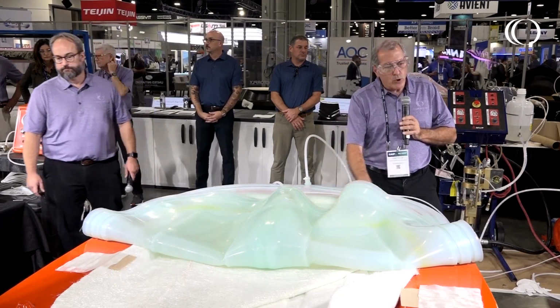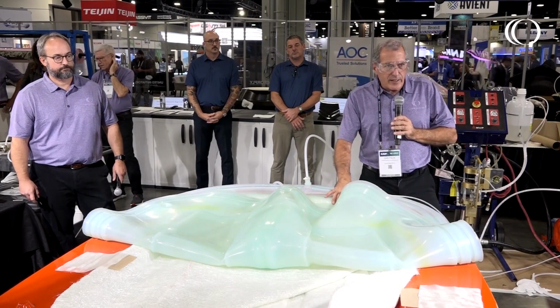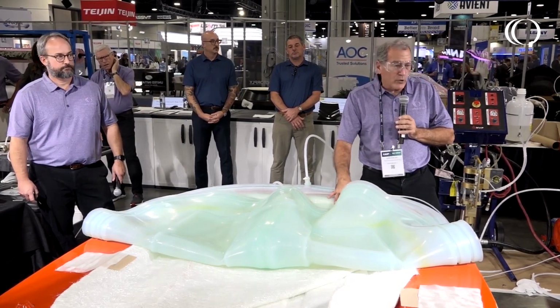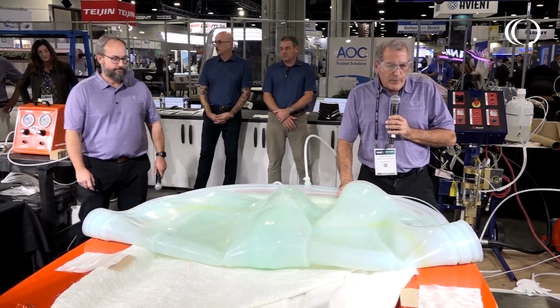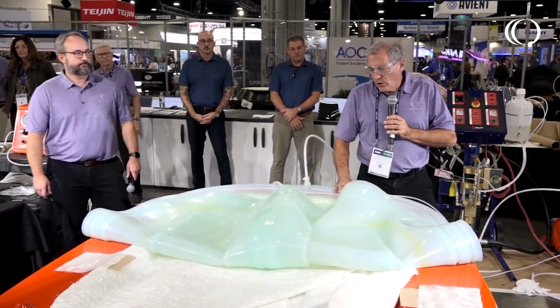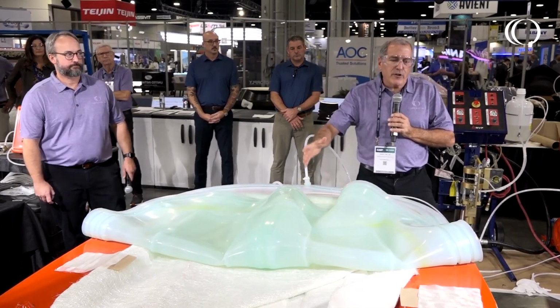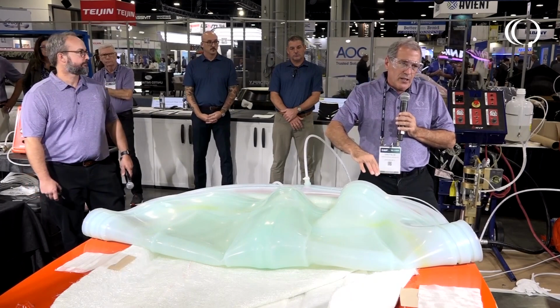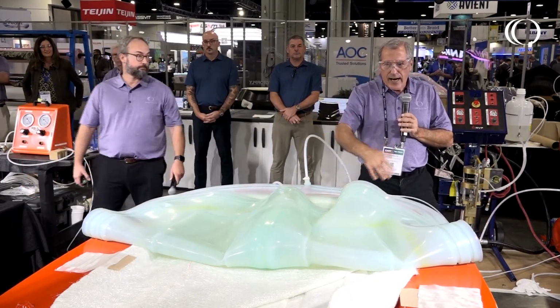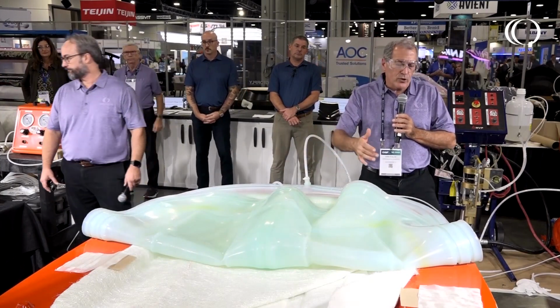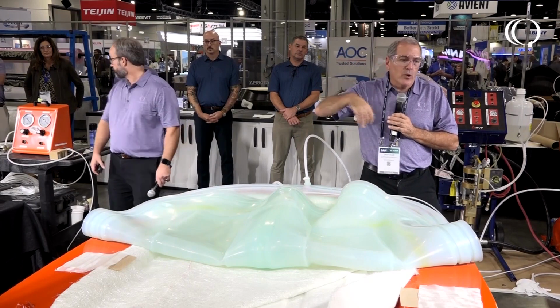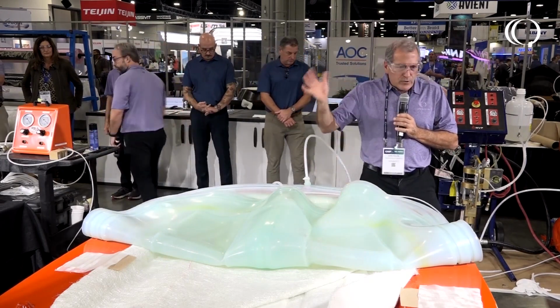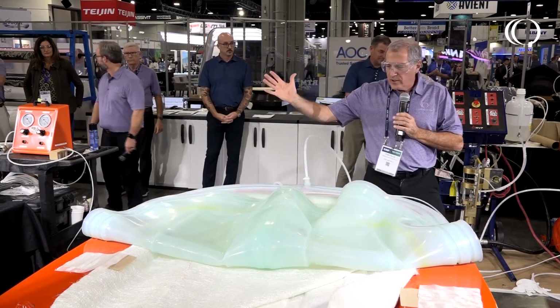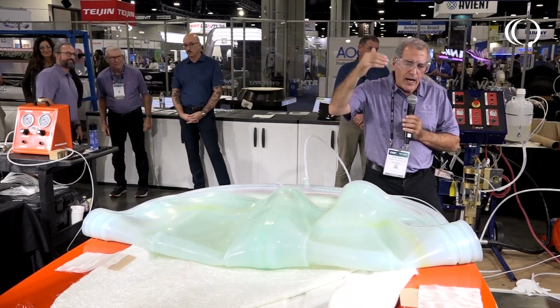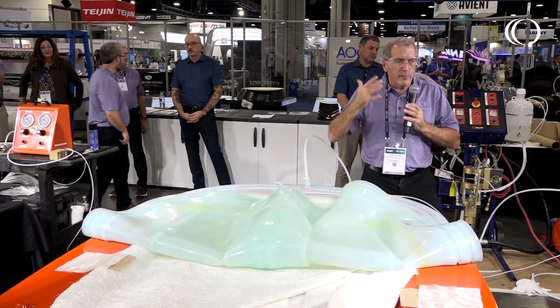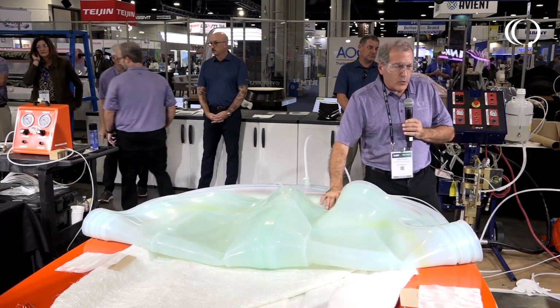One of the great things about swirl is you don't necessarily need any kind of fabric reinforcing. A lot of the bagging systems you have to reinforce with a fabric mesh. The swirl you do not. The swirl material also is very forgiving in the fact that you can spray and you can leave and go to lunch, come back in an hour and start spraying again, whereas a lot of the 10-to-1 materials you have a very tight window where you need to put the next application on. Swirl is no different except for the fact that the window is wide open. It's at least 24 hours where you can apply and the material bonds to itself and becomes homogeneous to itself and becomes one. So it's one of the real nice things.